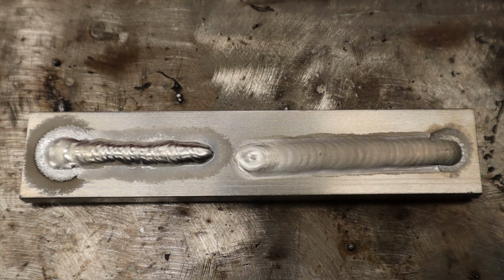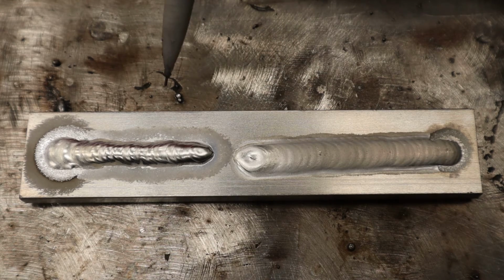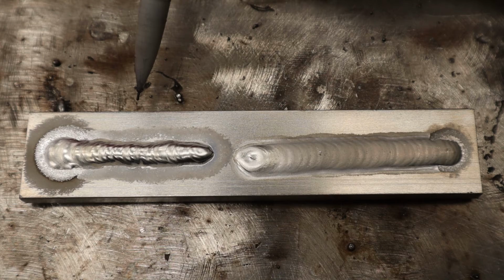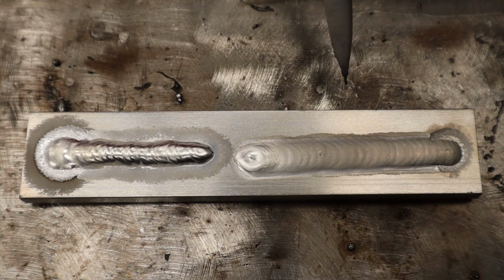So once again, with these samples here, I have decided to make two polar opposites so that you can kind of see what happens when you go towards one side or the other. Now, the adjustment that I made on this one was only my AC balance. So this one here, I have gone with a max cleaning side. So on my machine, it's close to 60% positive, 40% negative. And on this side is the maximum penetration, which is going to be 80% negative, 20% positive.